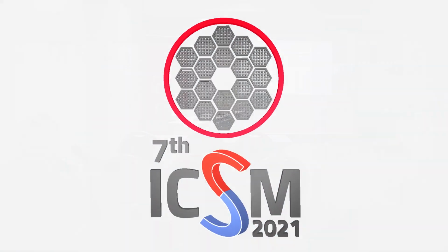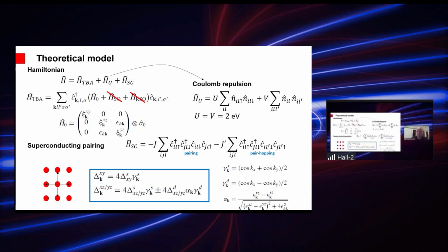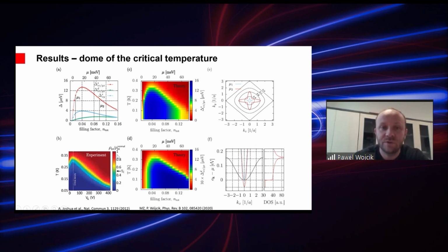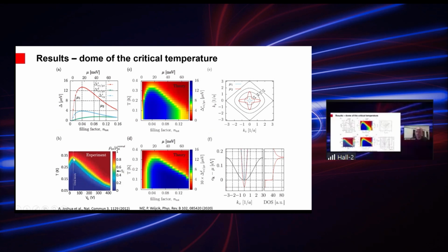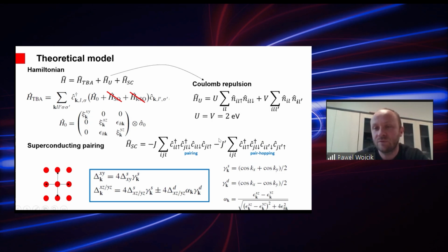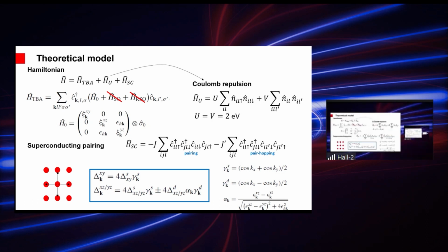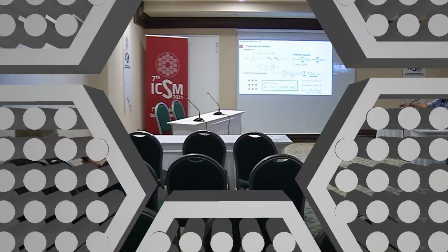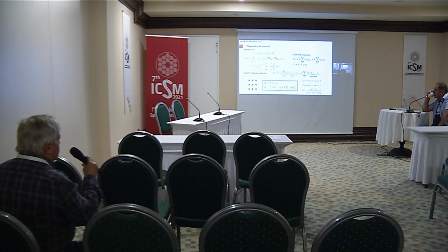Of course, in our model, the J is just a parameter. So in fact, we just set J in order to get the critical temperature exactly the same as in the experiment. Okay, thank you. So it is not very high, but the J prime is always one order of magnitude smaller, but this term guarantees that although in different bands we have a different energy gap, we still have exactly the same critical temperature for all.